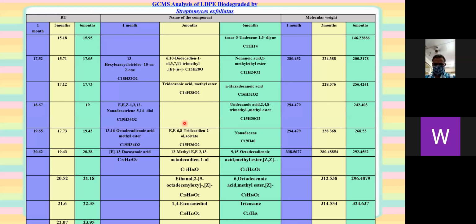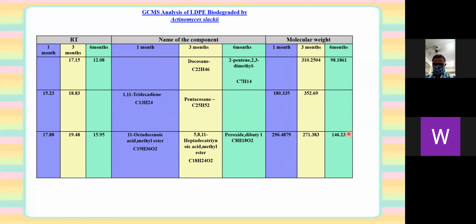Next, GC-MS analysis of LDPE biodegraded by Streptomyces exfoliatus. This is the RT value, the name of the component with molecular weight. We can see the formation of many low molecular weight oligomers, and there is a reduction in carbon bonds, and a reduction in molecular weight can also be observed. The molecular weight reduces as the incubation time increases. This is in the case of analysis by Actinomyces slacki.